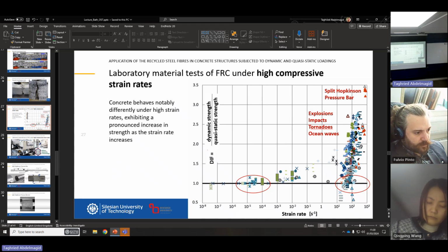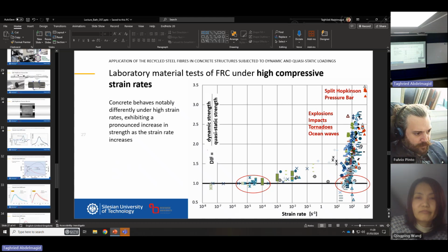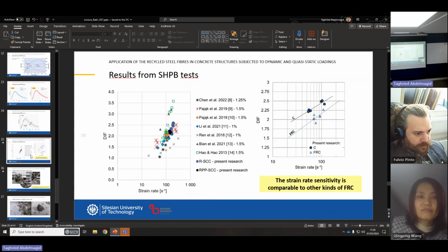Let's say it's complicated. So we are not able in the tests to achieve values that are not affected by the contribution of radial forces. It is called radial confinement. So when we have a big influence of this radial confinement, we are not able to test the influence only of the fibers. The only results that we are sure of, I will show you, it's that the fibers.